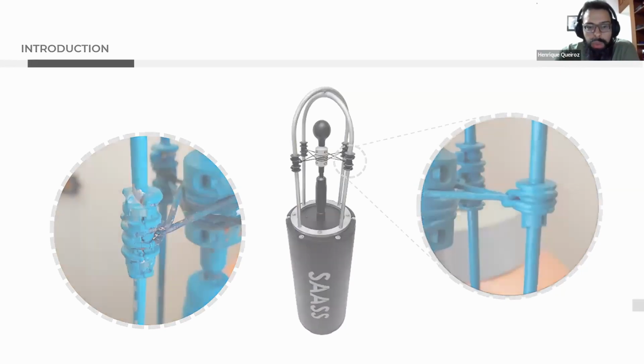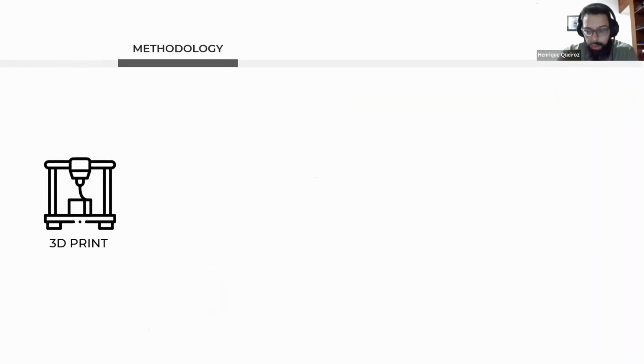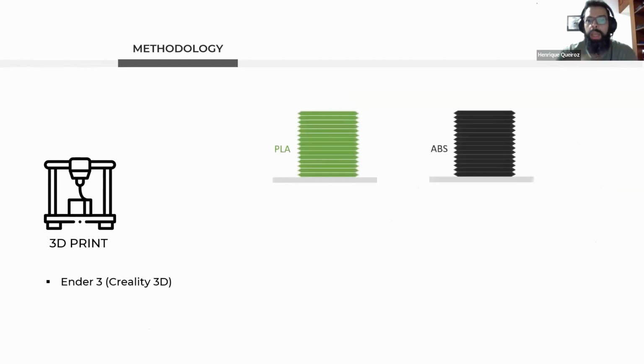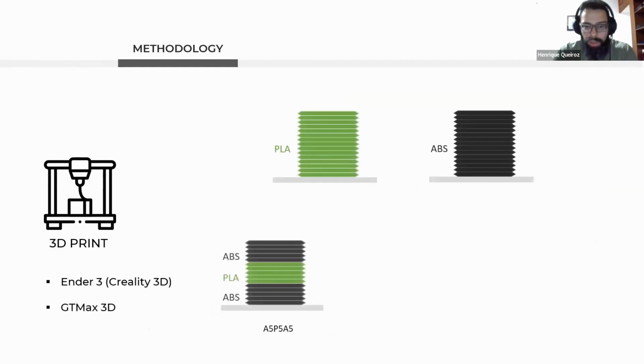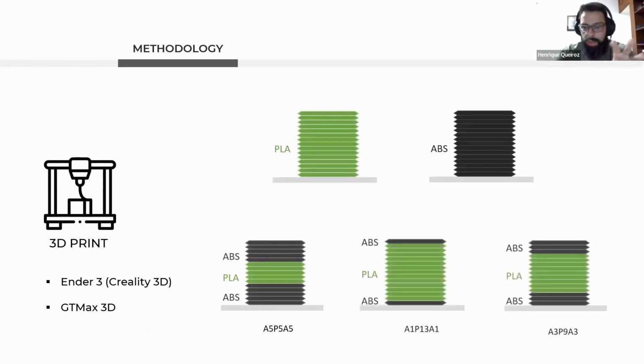And so the idea was, what if we used the 3D printed technology to create a hybrid material, right? So you have the PLA or ABS, and you also have structures that are essentially sandwiches, right, of PLA and ABS. Now, why do that? Well, if you look at the literature when it comes to FDM, both for ABS and PLA, what we see is that ABS absorbs less moisture, and it tends to maintain its mechanical properties much more effectively than PLA. PLA is very significantly affected by the marine environment, aging, right? Not even marine environment, just like normal water environment.